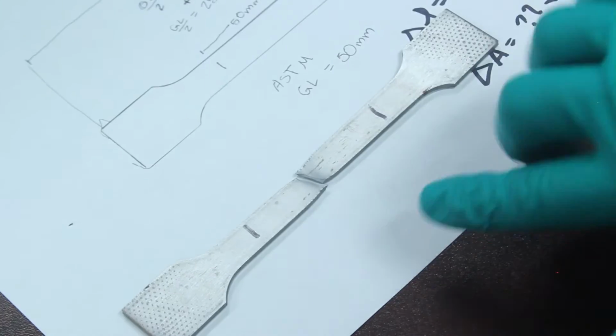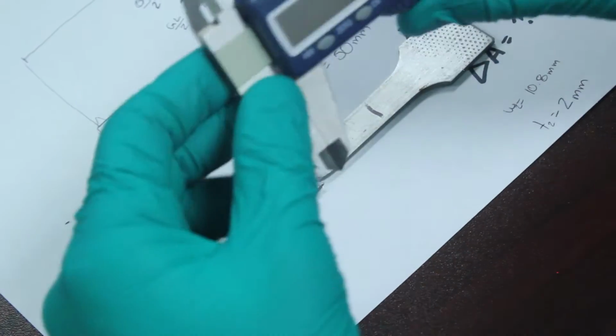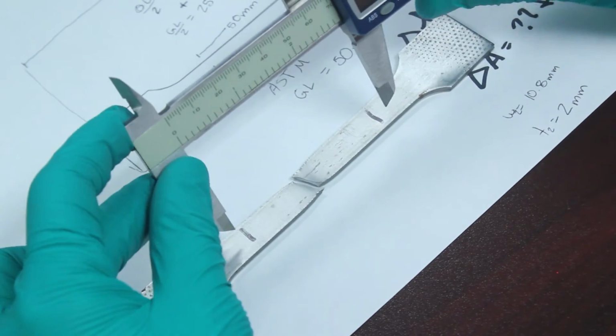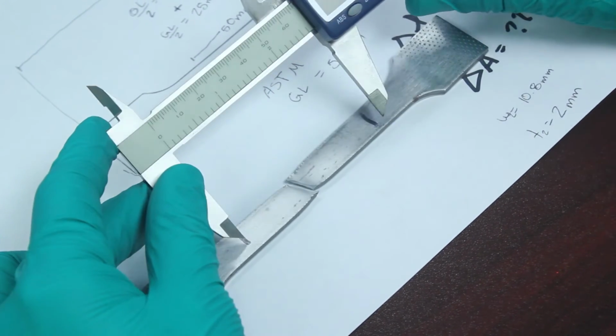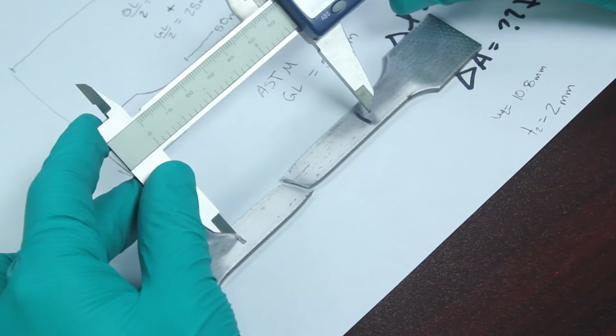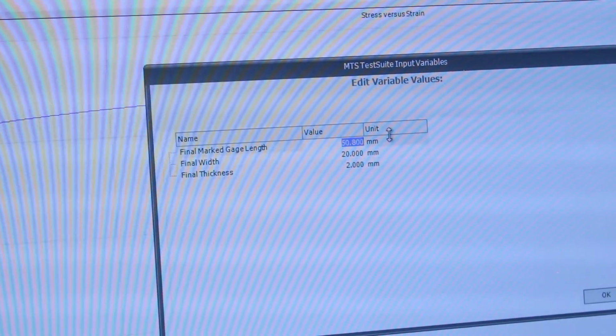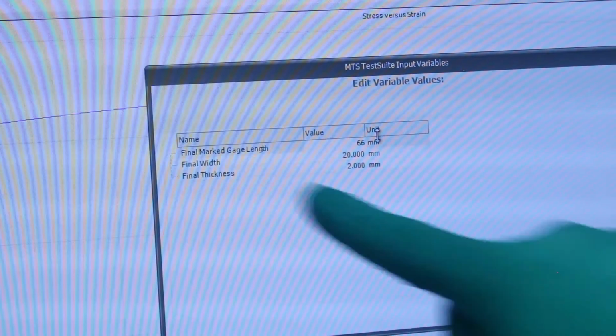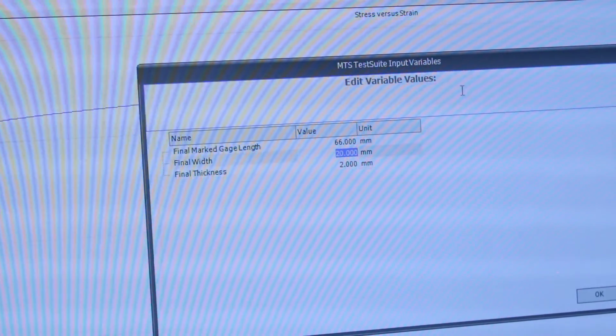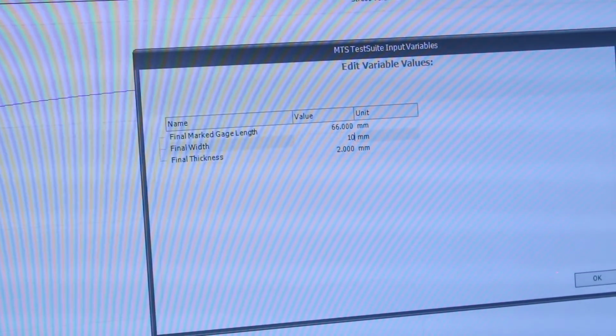To measure the final length of your tensile sample, place the two halves up against each other with the fracture surfaces touching, and then measure the length between the two black Sharpie marks you marked at the beginning. Input the results of your measurements into the boxes that show up after the test is completed on the computer.